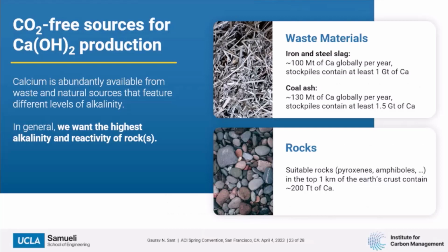So an important question that really comes up is, do you have enough calcium around? The short answer is absolutely yes. You can look at quantities of slag and fly ash. There's not that much. But you know what? There's give or take a couple of gigatons of calcium in slag and fly ash around the world. The real opportunity is around rocks. Look at pyroxenes, look at amphiboles, look at basalts and the like. There's about 200 teratons of calcium contained in just these reservoirs alone. Really important to keep in mind, because there's lots of other things that you could go to get calcium out of. You want to select rocks to get essentially the highest alkalinity and the highest reactivity. But the good news is once you do this identification, you've got sources of calcium other than limestone that you can start to use.